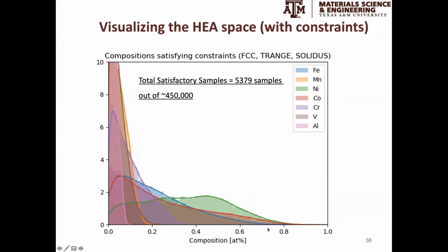Here we have the compositions of the different elements. The way we read this histogram is the following: here we see aluminum in pink. In the universe of alloys that satisfy all these constraints—basically 1% of the total FCC space—all the alloys have to have less than 10% aluminum. There's no alloy with more than 10% aluminum that also satisfies these constraints.